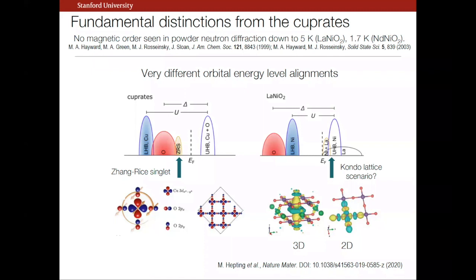Okay, Gabi? Is there anything known about the magnetic stability and magnetic properties of these type of compounds? Okay, again, is anything known about the magnetic susceptibility and magnetic properties of this class of compound? So, not reliably for our films because we're dominated by the substrate. Bulk powder work is very difficult because even in the best work, I mean, it was very brilliant work in Liverpool, there's a few percent secondary phase, which tends to be magnetic. And certainly that's the agenda of my colleagues like Wei Sheng to use RIXS to go after looking at magnetic excitations, but you know, to be done.